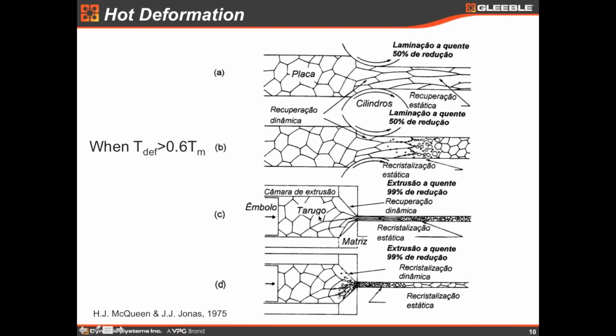So if you go to a very high deformation in extrusion, in a high stacking fault energy metal, like aluminum, the deformation is so high that we create so many dislocations and driving force that we have static recrystallization after the deformation. And if we have low stacking fault energy, we start having the recrystallization in the deformation zone. So this is dynamic recrystallization, and we will follow during the interpass time with metadynamic recrystallization. So this is basically a summary of what can happen when we do a hot deformation in a metal.